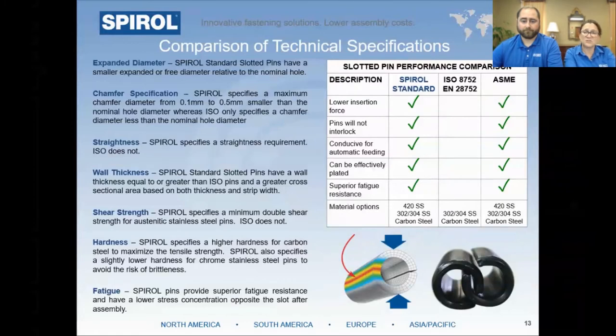And if you experienced issues with slotted pins failing in shear or fatigue, it could be because the ISO pins have more stress in the spine of the installed pin due to the larger free diameter. A simple fix in many cases could be to ditch the ISO 8752 pin and replace it with either the ASME or the SPIROL standard pin, which are drop-in replacements for all diameters except for the little teeny tiny pins less than 3 millimeters in diameter.